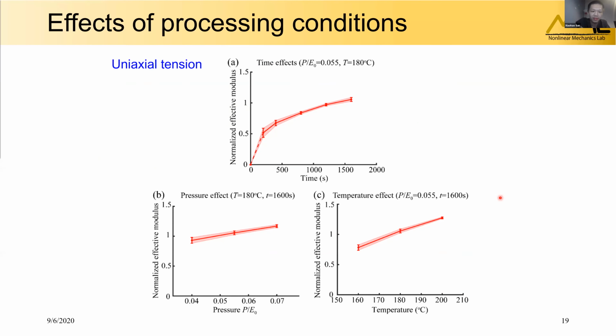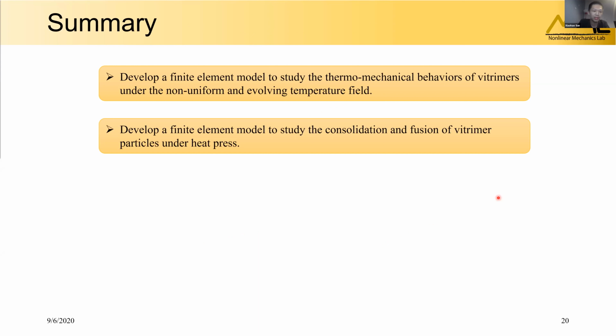So here are the effects of the processing conditions. We obtain the general trend consistent with the experiments that the longer healing time, the higher pressure and higher temperature can lead to samples with higher modulus. So here is a summary.